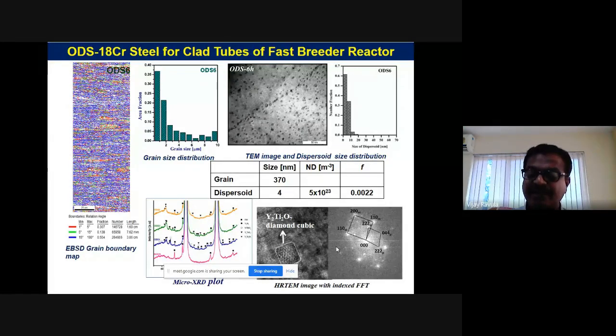So that's why they're not simply dispersed. Generally, dispersoids will not have any orientation, but here they have an orientation. So that means they are actually a precipitation of an oxide, not an intermetallic, not any of the carbides or nitrides precipitated, but an oxide being precipitated in this material. Right. And that's why they are all finer.